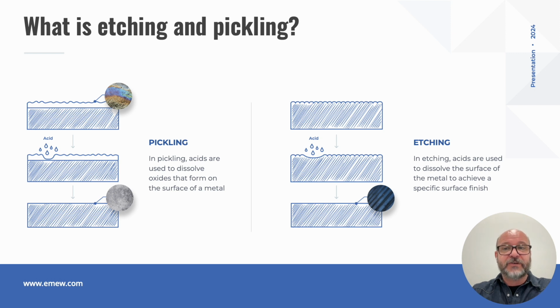Pickling is considered to be a heavy treatment in that a significant amount of metal can be removed or dissolved from the material being pickled, typically on the order of grams per square meter of surface area. Etching also requires the use of acids, but the difference is where pickling removes these oxide layers and areas of elemental enrichment or depletion from the material, etching imparts a very specific surface finish in the production of battery or capacitor materials. For instance, the aluminum or copper that's used has to have a very specific surface roughness, and acids are used to impart that surface finish that's required for the application. In comparison to pickling, etching is considered to be a light surface treatment process where the material being dissolved from the material is typically on the order of milligrams per square meter of material.